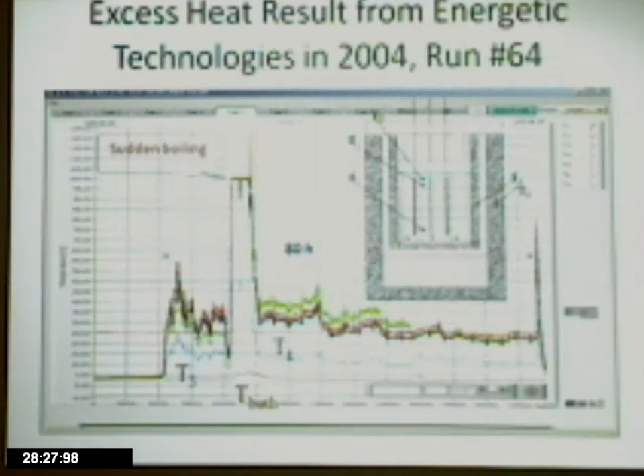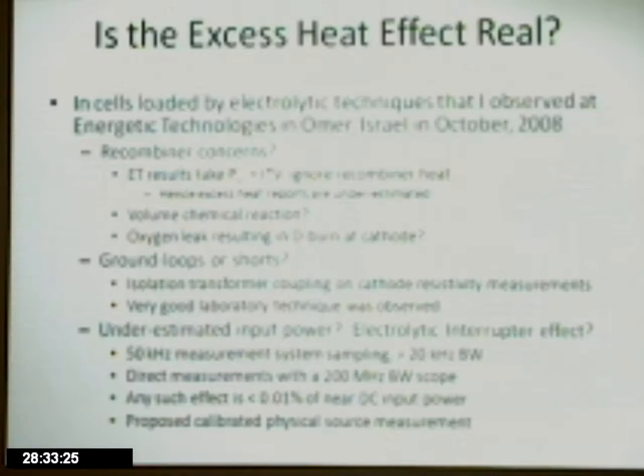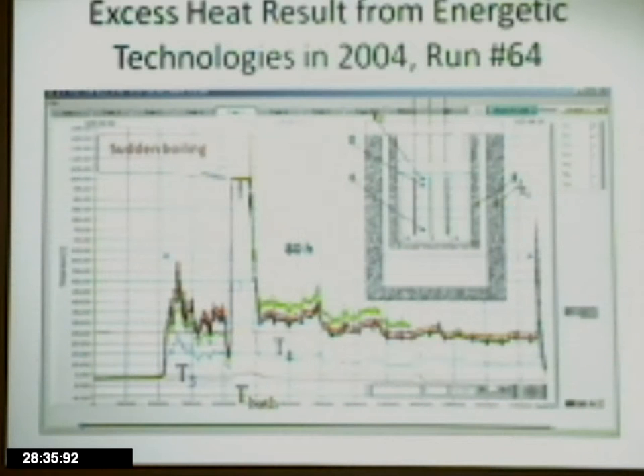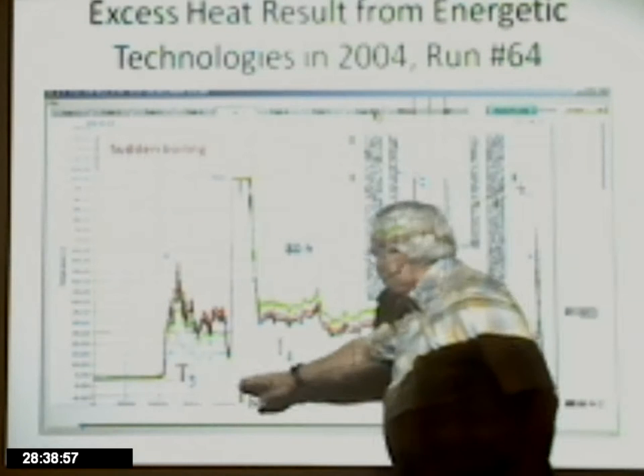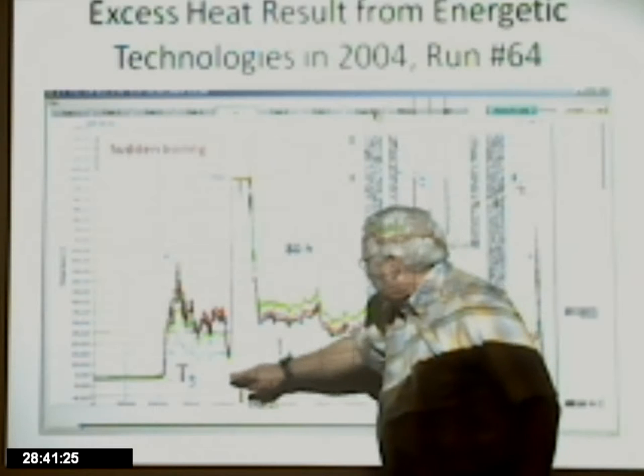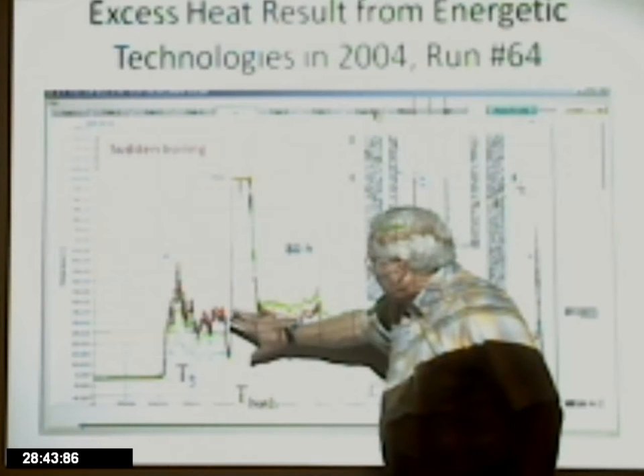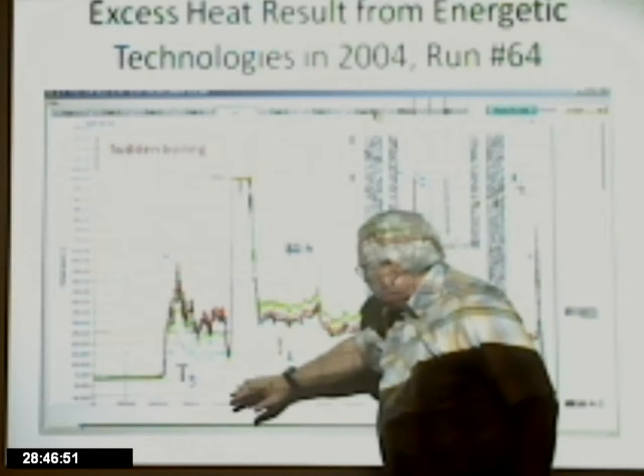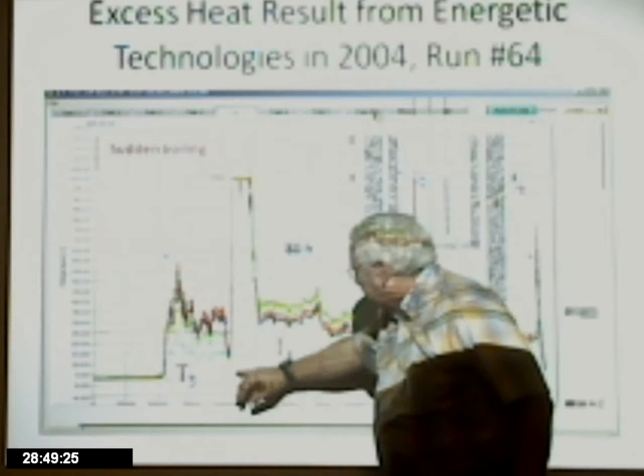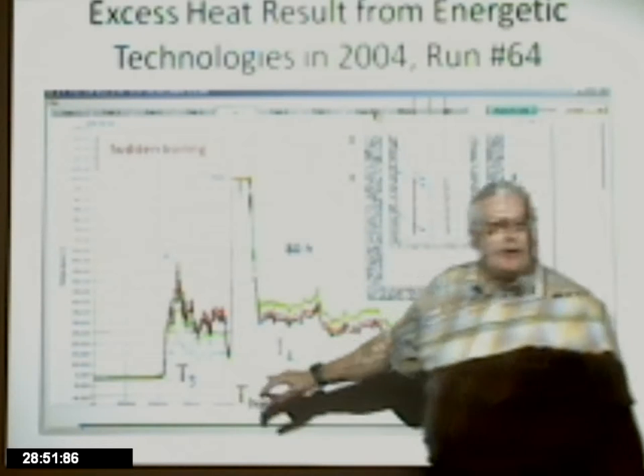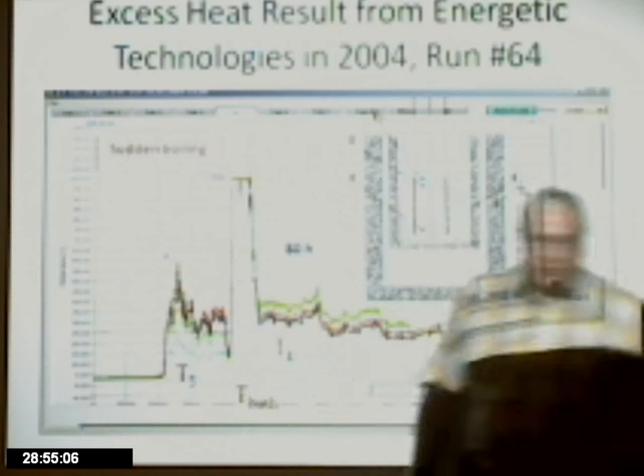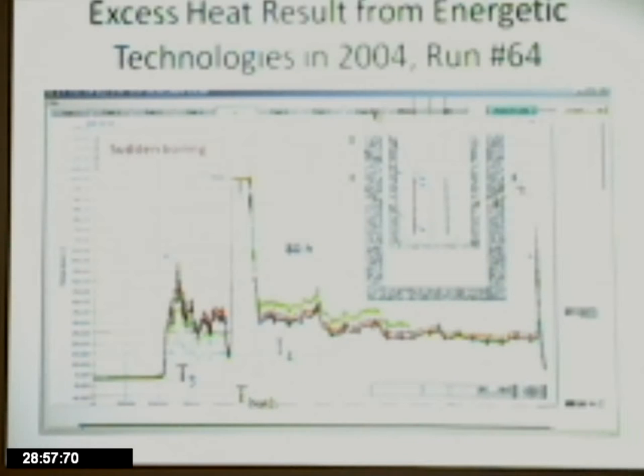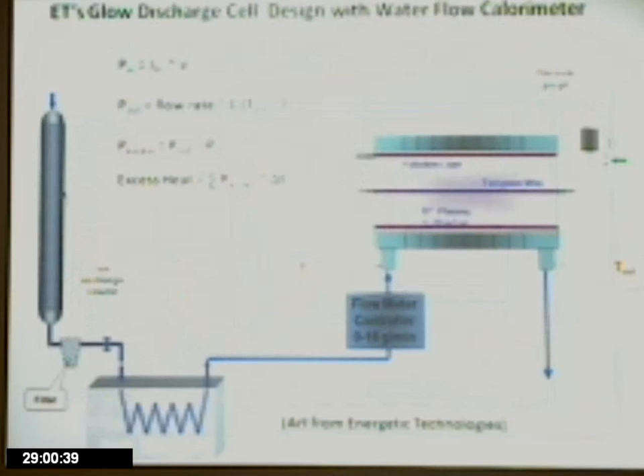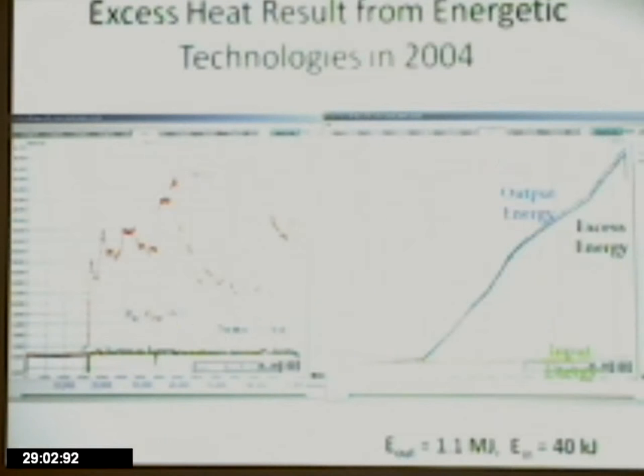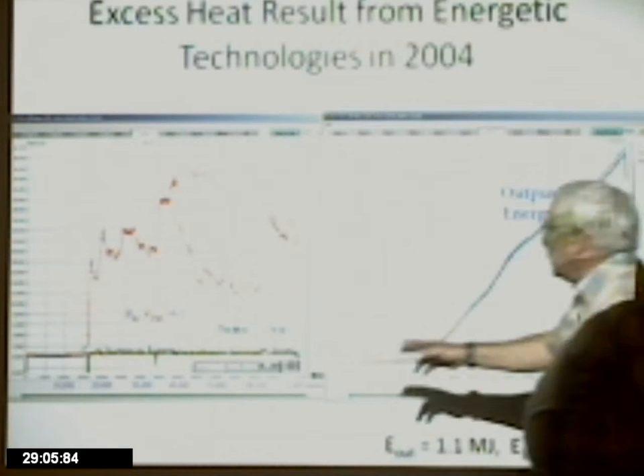But the interesting thing, I should go back and say, the one thing I thought was kind of interesting here is that during the time they had this really massive result, they had this whole thing in a Lauda, which is like a refrigerated bath, and the excess heat from the system out of its calibration range was so intense it ruined the ability of the refrigerator to hold its bath temperature. So the bump you see in the bath temperature is due to the heat load of this experiment during this release.